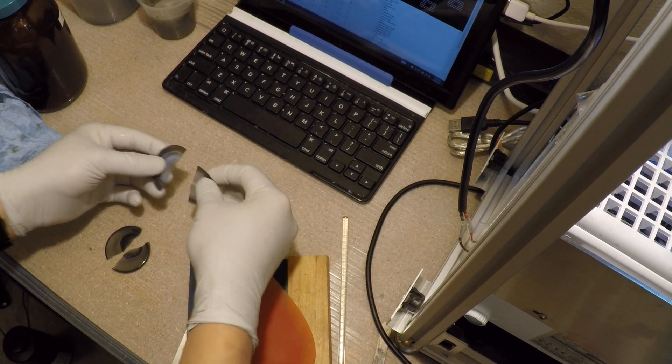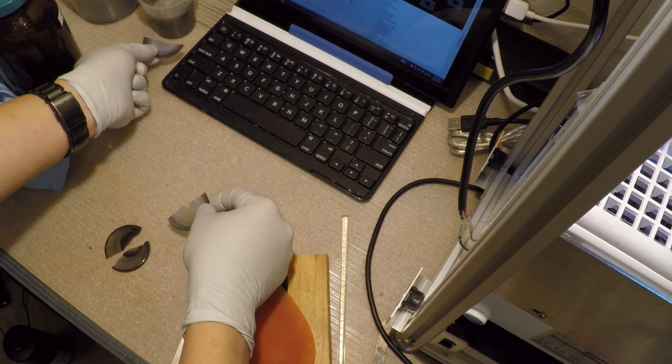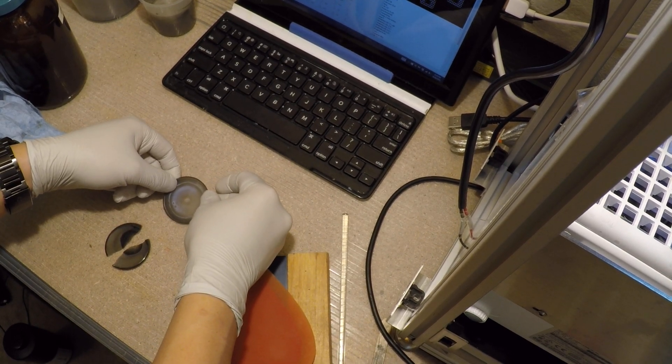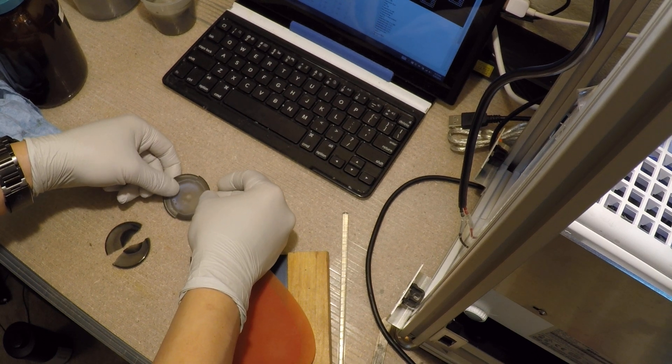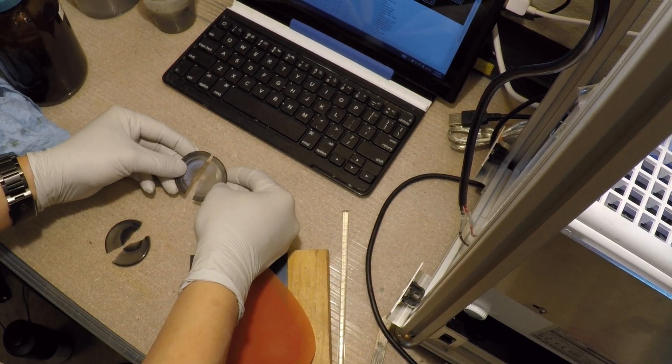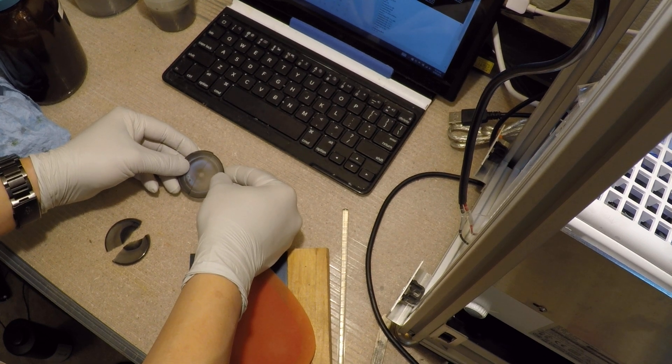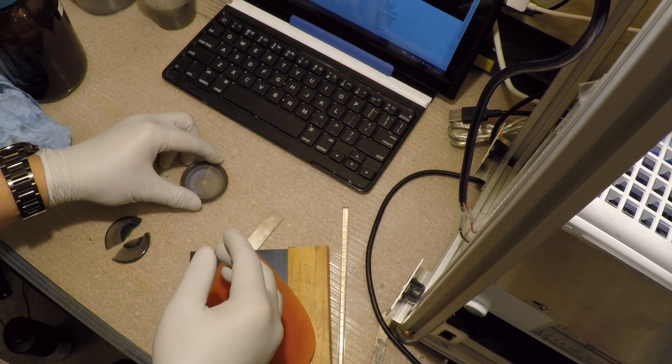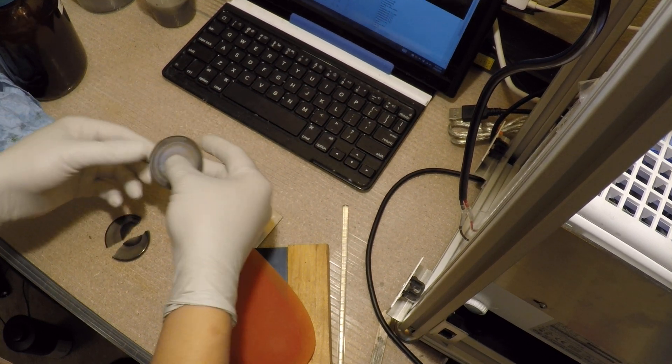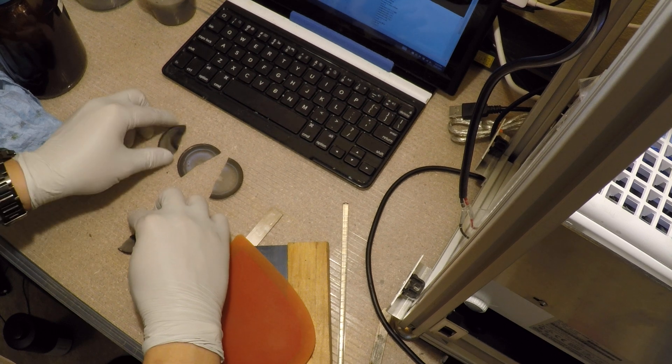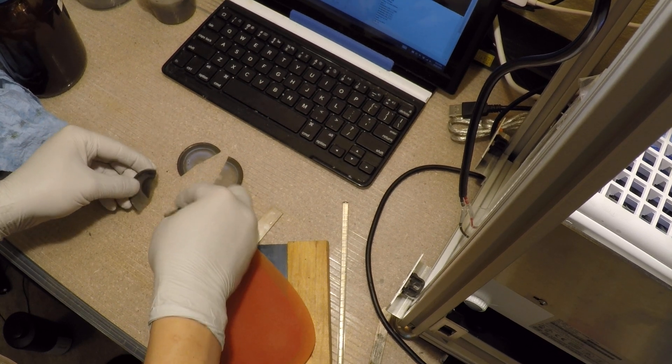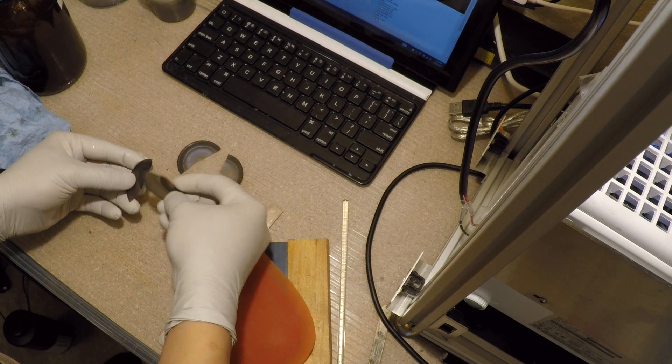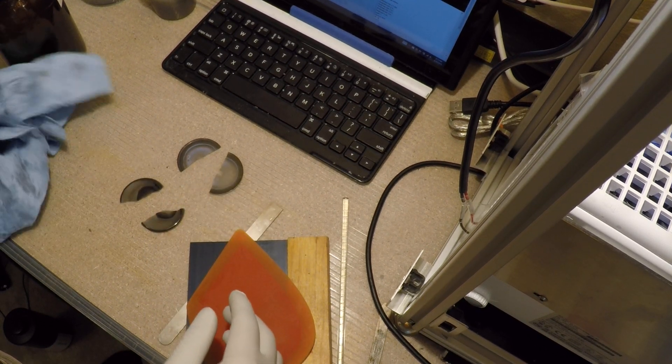I was testing. I basically put a little bit at the bottom and then cured a disc with a UV curing chamber and then followed all the usual finishing. And so I cured it for like an hour, pull it out, rinse it off in IPA, put it back in under water for another 30 minutes to get these guys fully solid. And there's a couple of interesting things, interesting differences between these.